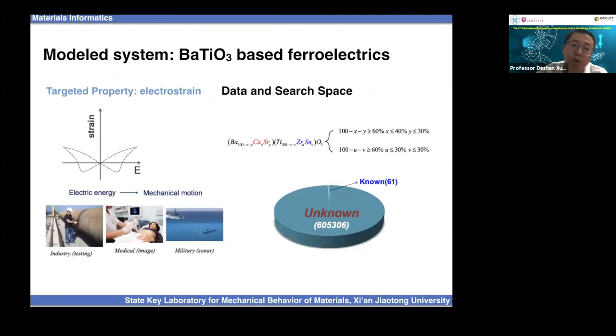So we use a model system of barium titanate-based ferroelectrics to benchmark our approach. The targeted property here is the electrostrain. So this kind of material can have strain if we apply the electric field. So we want the strain as high as possible so that we can make the device smaller.